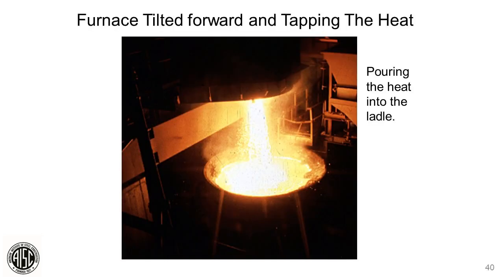Okay, last question. I've got an image up here of the heat being poured into the ladle, and the question is: how does the ladle not melt? Right. Like I said, it's a steel vessel, but it's lined with refractory brick, almost a thickness of 12 inches all the way around. So that whole thing is bricked on the inside with a high-temperature refractory material. You can't melt it.